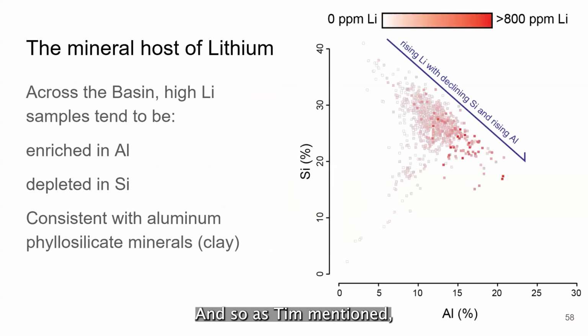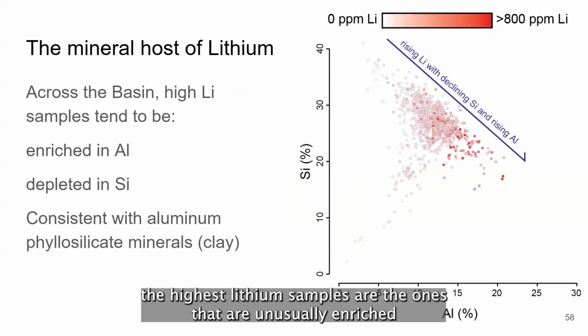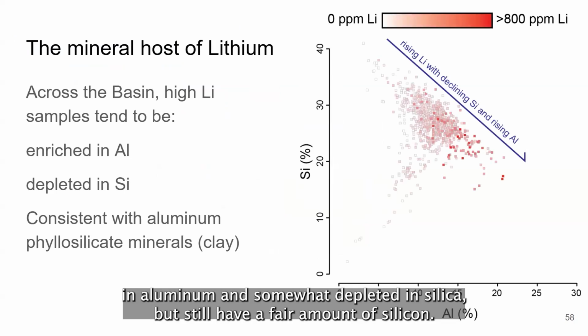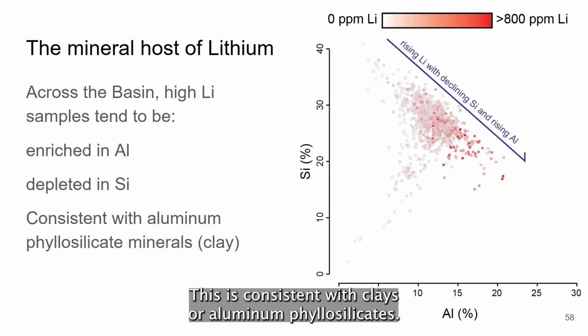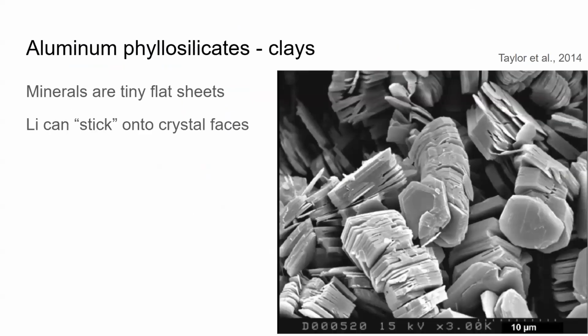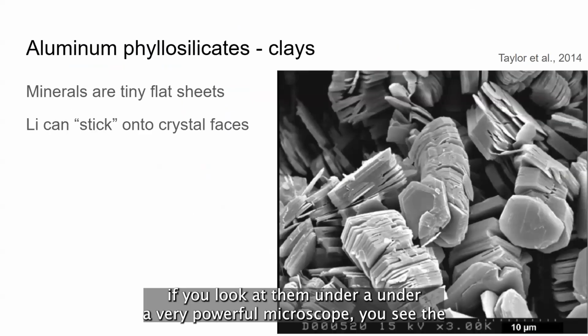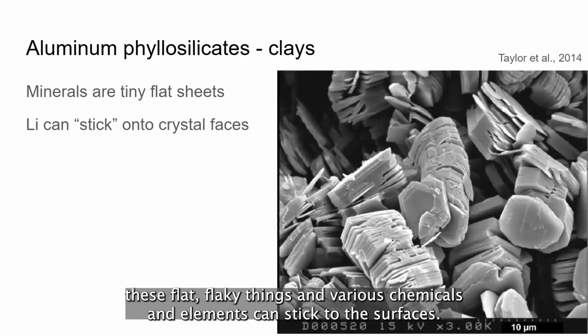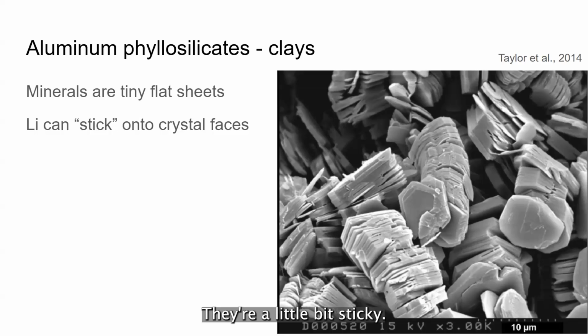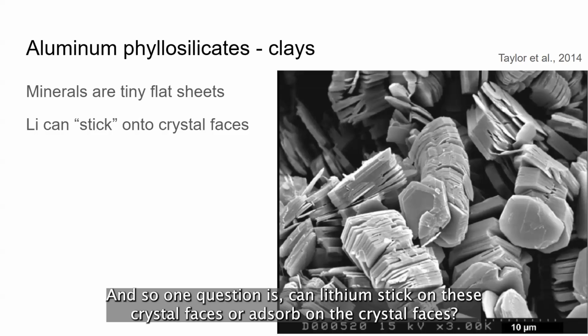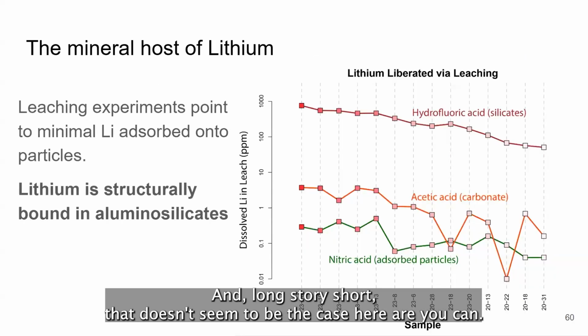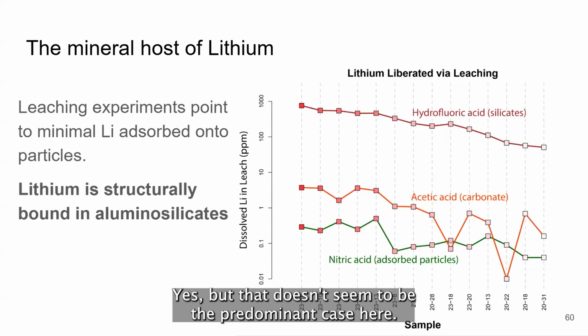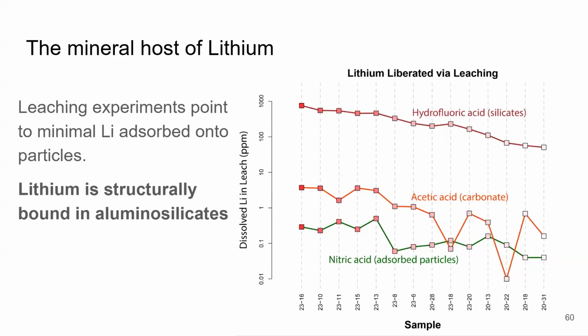And so, as Tim mentioned, the highest lithium samples are the ones that are unusually enriched in aluminum and somewhat depleted in silica, but still have a fair amount of silicon. This is consistent with clays or aluminum phyllosilicates. These clay minerals, if you look at them under a very powerful microscope, are flat, flaky things, and various chemicals and elements can stick to the surfaces. They're a little bit sticky. So one question is, can lithium adsorb onto these crystal faces? Long story short, that doesn't seem to be the predominant case here.